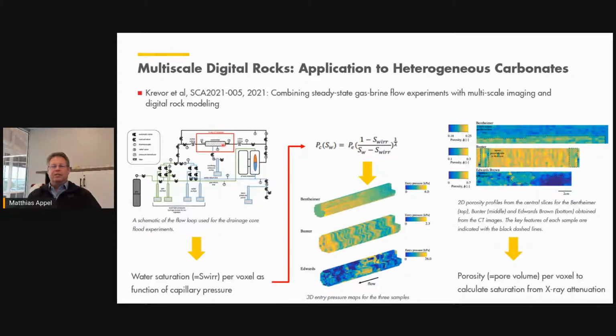The micro CT scanner is used in combination with what's called wet and dry scanning, where basically the core is scanned twice, once without fluid in it, second time with fluid in it. And from the difference images, one can determine the fluid saturation at each voxel. In parallel to that, the rock is also scanned for its porosity distribution. Here are the 3 different samples where that has been done. And then by combining the information at each voxel and assuming a certain capillary pressure behavior, one can determine the capillary pressure, the entry pressure in each of these voxels that are measured.